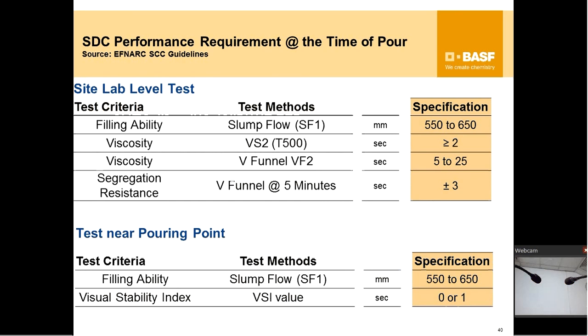What we do here is the same V funnel, but after pouring it in, keep the setup aside for 5 minutes. Don't touch it for the next 5 minutes. After 5 minutes, you open the trap door and check how much time it takes. Say the initial V funnel at 0 minutes is 20 seconds, then the V funnel at 5 minutes should be plus or minus 3, between 17 and 23. The reason is, if the concrete is segregated, it will settle to the bottom and choke the concrete at the opening. So you will very clearly know, if the time goes up by more than 3 seconds, the concrete is segregating, and this concrete has to be discarded, it is not allowed.